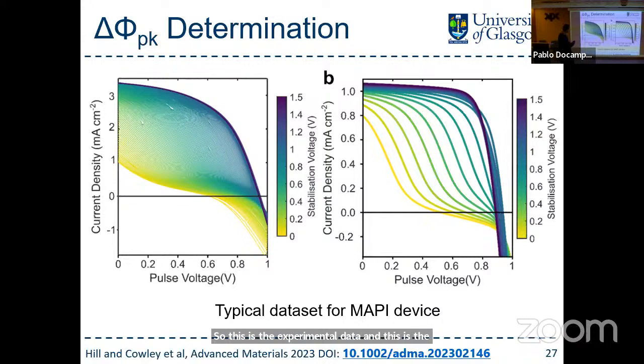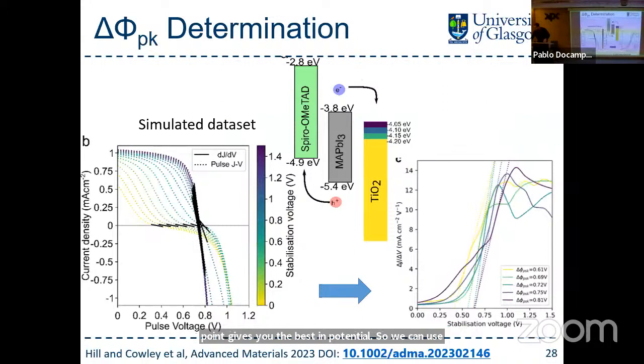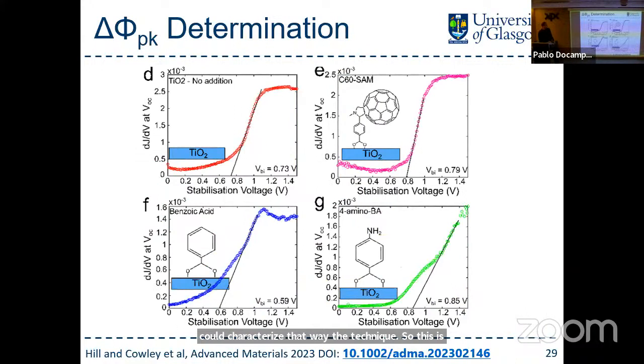The main thing here is that this goes from being quite S-shaped to being quite sharp, and there's a transition point between the two. The transition point gives you that built-in potential. So we can use that to characterize a cell. We did some simulation work where we changed the offset of the contact on one of the interfaces and saw if we could characterize that with the technique. This is the prediction from the modeling. This is the actual result.